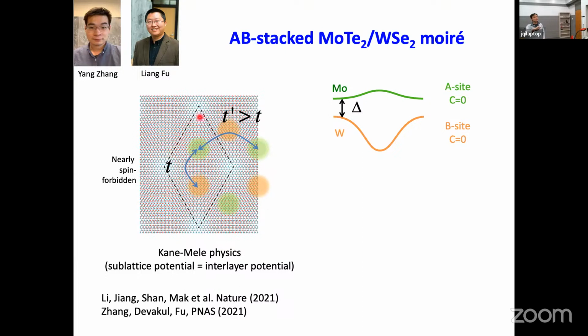And then the next nearest neighbor hopping T prime, which is oddly, in this particular compound, bigger than T, is the intralayer hopping only within the layer of that band. In some sense, this T prime is basically producing the bandwidth of each band, and T is smaller than T prime. So effectively, the low energy physics of these two bands can still be mapped to a Kane-Mele model.